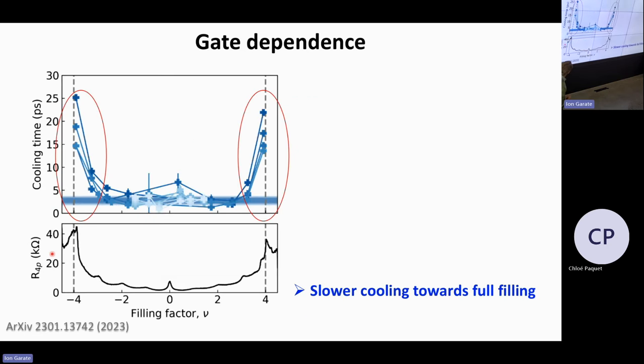So we studied a little bit more, because of course we have this gate tunability of the system. So what we did here is we started to look close to a filling factor of 4. So this means that the whole Brillouin zone is filled with 4 electrons. And what you then see, so basically we're just changing the Fermi energy. And this is like the maximum filling of the Brillouin zone. And what you see is that both with holes and with electrons, what you get is much slower dynamics when you're close to this full filling.